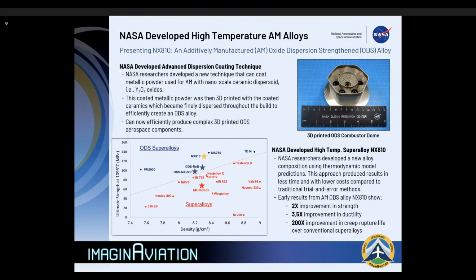And through some trial and error, we were able to find parameters that were able to take that coated yttria and break it up and fully disperse it randomly into our AM build. And so we had just basically nanoscale oxides throughout our microstructure. They're not agglomerated on grain boundaries or even throughout the metal part itself. So just nanoscale nickel, cobalt, chrome ODS components.